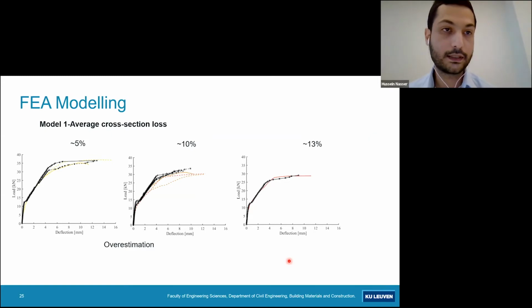I will now discuss 3 types of corrosion models. The first model takes into account only the average cross-section loss, the damage relations related to the steel material properties, and doesn't take into account the bond loss. It can be seen that a good agreement has been found for the high corrosion level, whereas for the lower corrosion levels, 5%, and the medium corrosion levels of 10%, if you remember previously, those two levels I showed the formation of splitting cracks. A little bit of overestimation has been obtained, which can be due to the fact that in these models the bond deterioration has not been taken into account, which would affect the stiffness and also the capacity.